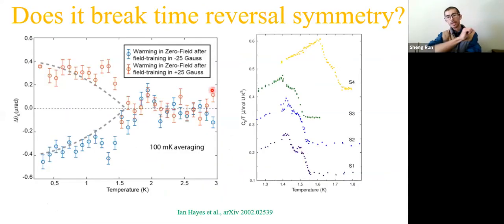Okay, if indeed we have a chiral surface state, then you should have time reversal symmetry breaking inside the sample. So do we really have time reversal symmetry breaking? Again, we did this in collaboration with people in another group, done at Stanford. We did the Kerr effect. The Kerr effect will tell you whether you have time reversal symmetry breaking inside the sample. So you have a polarized laser beam. If there is time reversal symmetry breaking, you will have a non-zero Kerr shift.